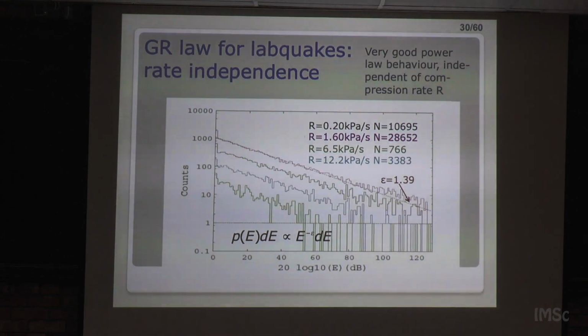Let's go to the test of the laws I was mentioning before. If you look for the Gutenberg-Richter law, you just make a histogram of the number of events as a function of the log of the energy, and you get this nice power law. There is an advantage here that we don't have with earthquakes, that is that we can control the rate. In earthquakes you cannot, but we can do the analysis at different rates, and you see that the exponent is not very dependent on the rate, except if you go very fast. When you go very fast, you start overlapping avalanches. The acoustic emission setup cannot distinguish them, and then you get distortions of this distribution. But there is a range of compression rates that gives a stable exponent, okay?